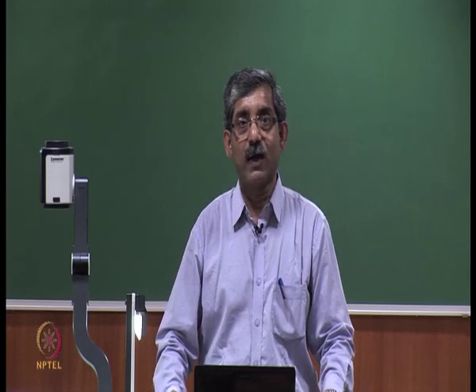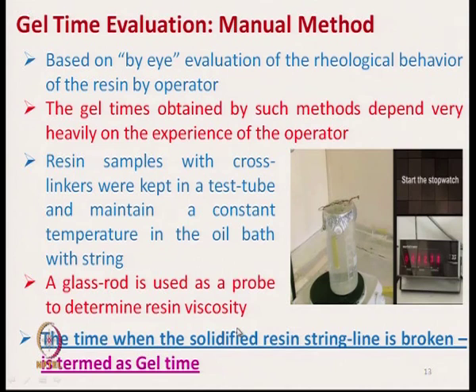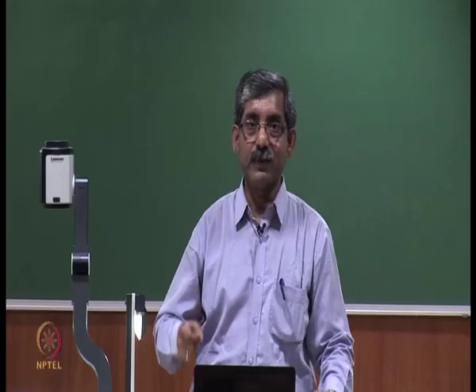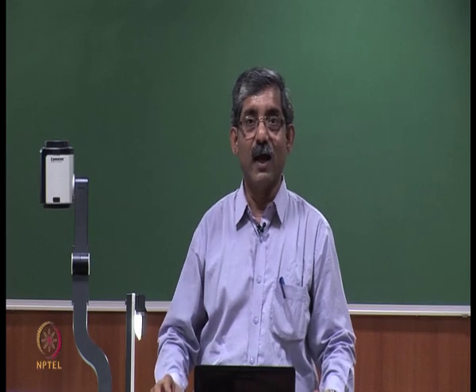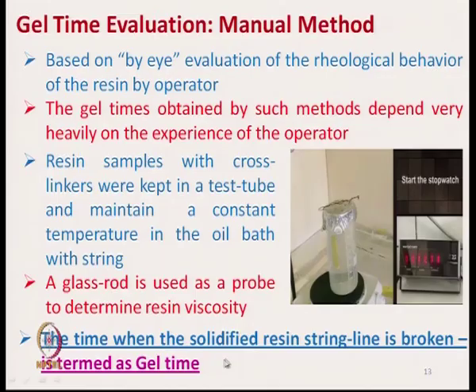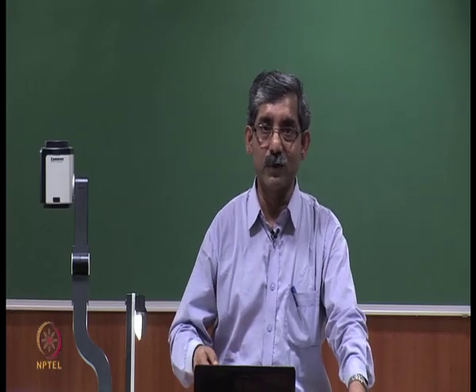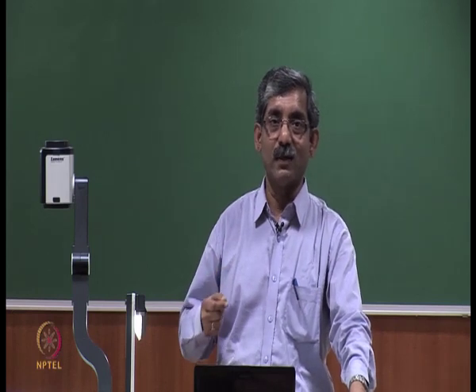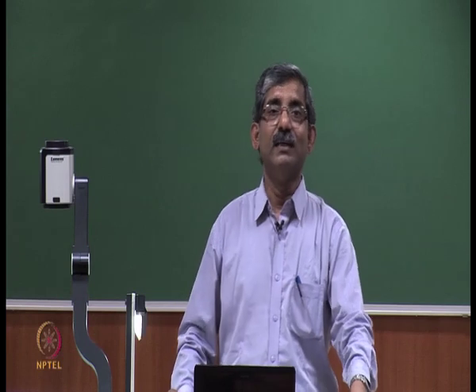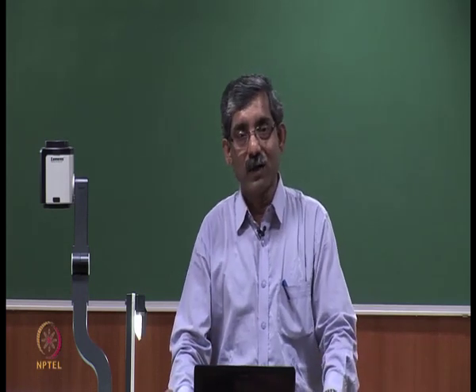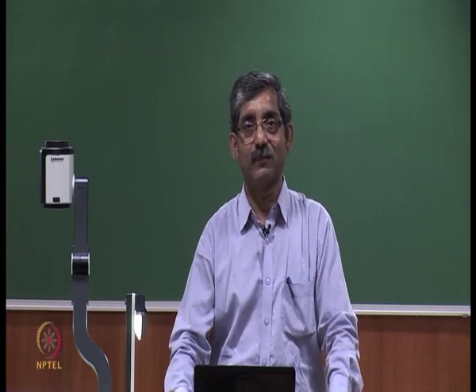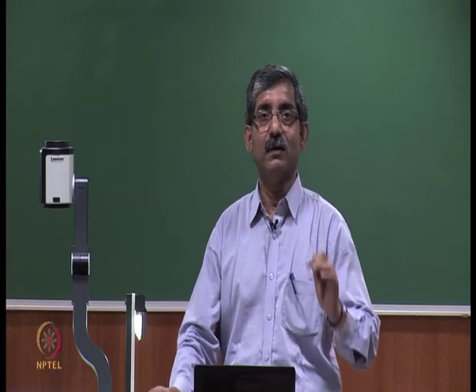A glass rod is used as a probe to determine the resin viscosity. So, it is stirred with the glass rod, and as viscosity increases, there will be resin string formation, and the time when the solidified resin string line is broken is known as the gel time. Before that, when the solidification is not completed, the string line will not be broken because it will be flexible, but as soon as the solidification is completed, the string line will be broken, and that time is recorded as gel time.